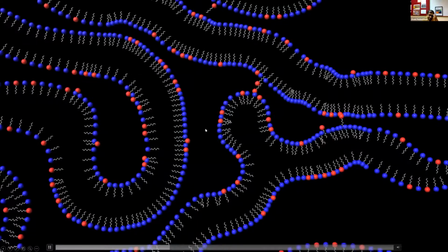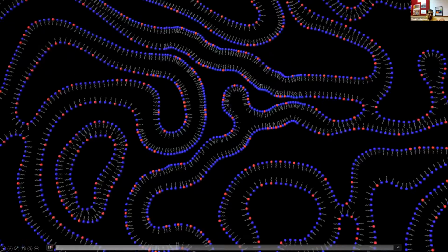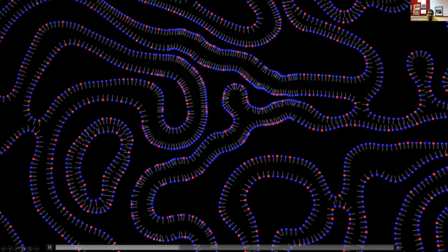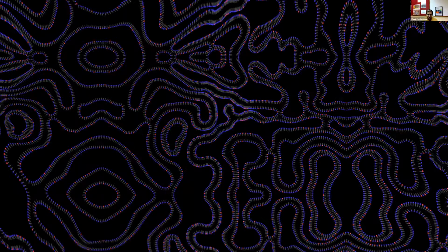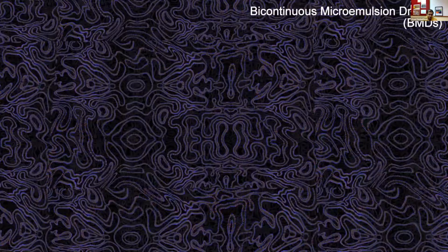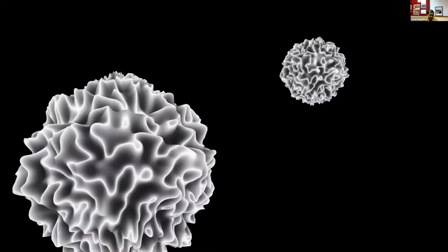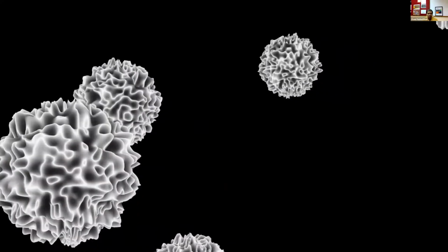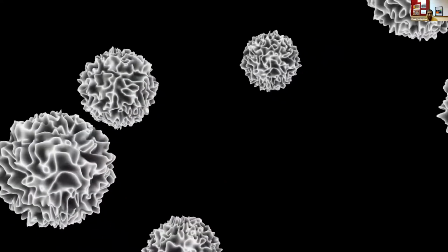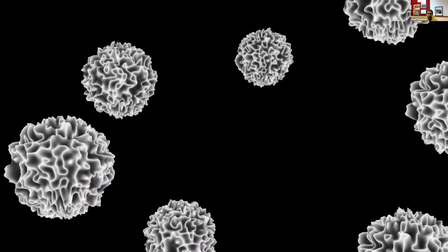And what we observe is that these are not floating flat in the solvent system, but they are in the form of a droplet. They are in the form of a bicontinuous microemulsion droplet, BMDs. So these droplets, which are made up of water, xylene, and the CTAB, are our reactor, our nanoreactor. And the water channels that you see, there we have the silica precursor TEOS and urea, which when heated converts